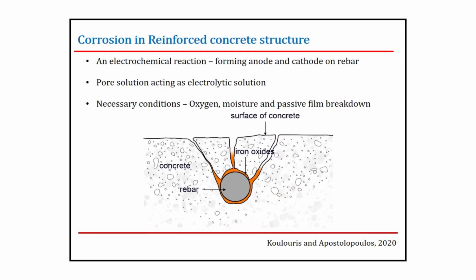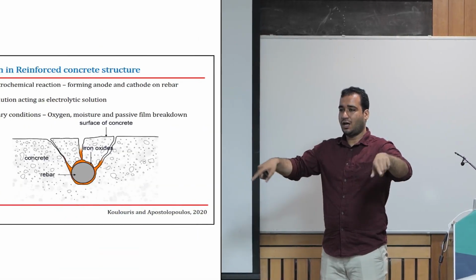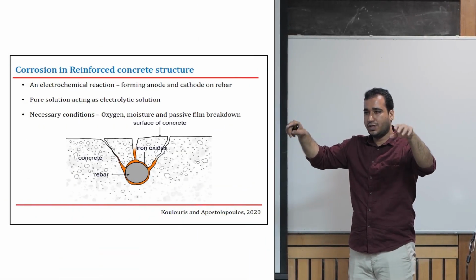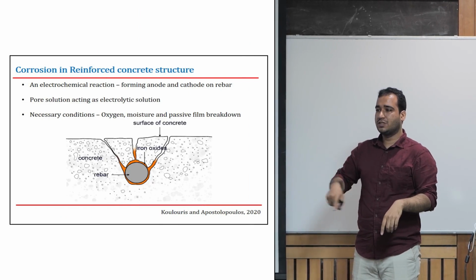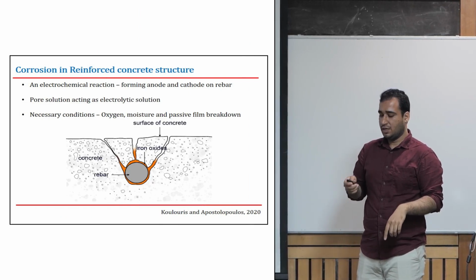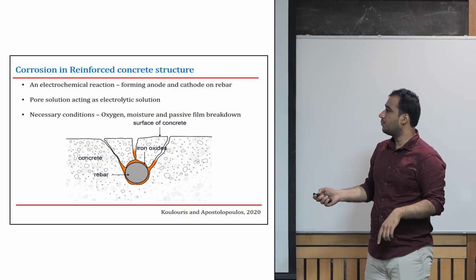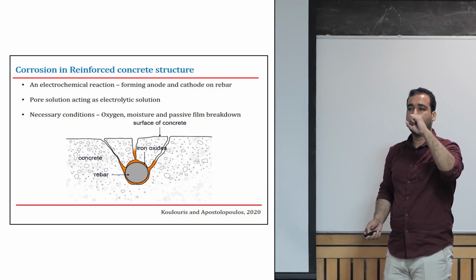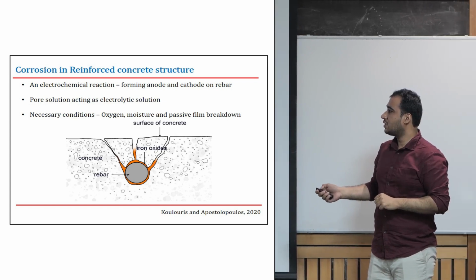Now let's see what corrosion is. Corrosion is an electrochemical reaction where you form anodes and cathodes on the same rebar, or on a different rebar, depending on your distribution of rebars. It can be either. Now, in any type of cell with an anode and a cathode, you will see a connection made outside with a wire where we monitor it, but inside there is also a solution which provides the connection for the ions to travel. In the case of our concrete, this connection is provided by the pore solution that exists in the pores of the concrete itself. This is the connection that works.